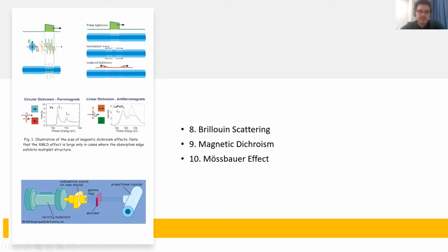And with this method, we can also study the buried layers or interface of our material. Mössbauer effect. In this effect, in one of the components of this AFM or FM material, an atom is replaced with its radioactive isotope. From this radioactive isotope, we can observe the radiated gamma rays, and so we can predict the characteristic of this location.